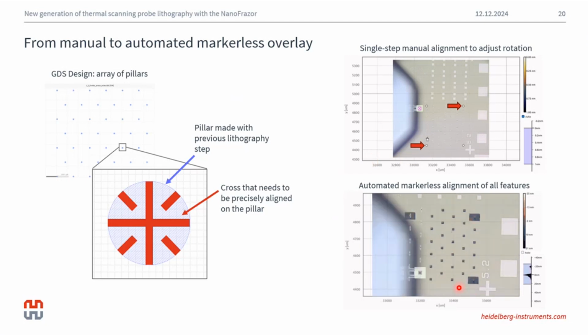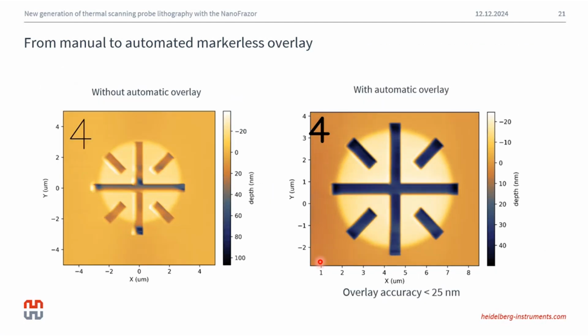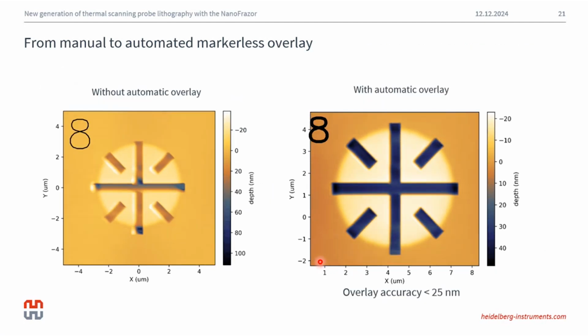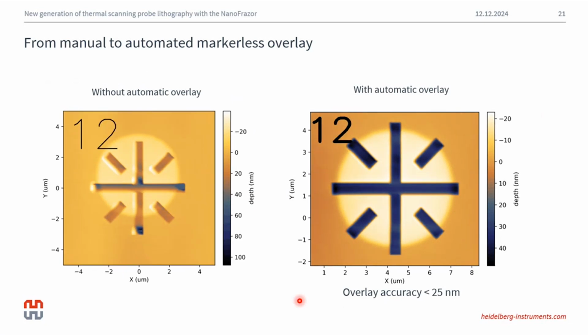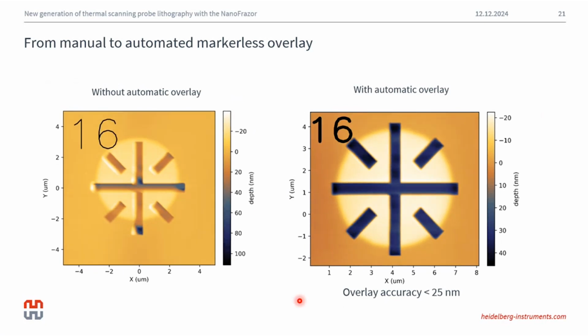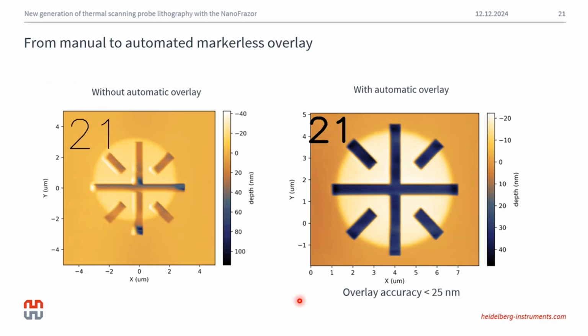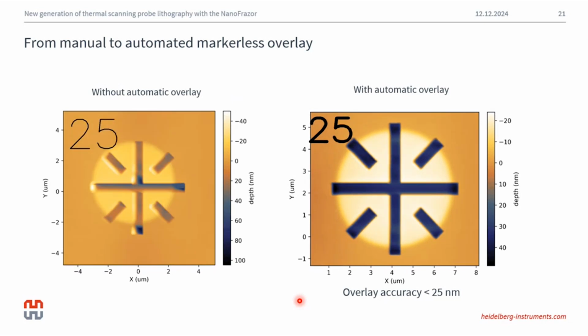Once this is done, we give the coordinates of all the remaining pillars, and we let the NanoFrazor tip move going from pillar to pillar, scanning the pillar, and then automatically aligning the cross or whatever feature there is to be written. You can see the resulting alignments here. With the automated overlay module, we can achieve routinely an overlay accuracy down to 25 nanometers.